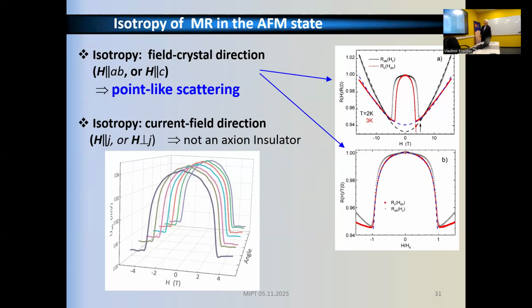Now, this was to show that we don't have an axion insulator, which was put forward in some papers which tried to explain this phenomenon. We rotate here the magnetic field relative to the current, and we don't see any signatures of strong anisotropy that should be intrinsic to an axion insulator. As I said, it is isotropic with respect to either current direction or field direction or whatever you think. It's an isotropic effect.